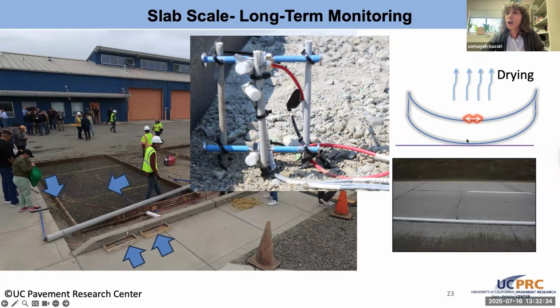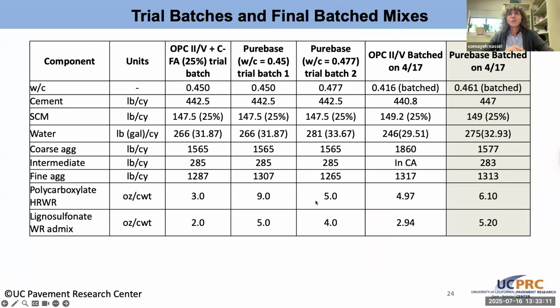As you can see, concrete slabs tend to curl upward as they dry more at the surface compared to the bottom. And because the slab wants to pull itself back down, and because the truck axles along the joints of the slab ultimately want to exacerbate cracking across the middle area of the slab, we're trying to monitor all of that curling and warping that may be happening across the slab. We're trying to monitor with these companion beams how much restraint from the weight of the slab and from the adjacent slabs influences that cracking and damage that may develop over time.